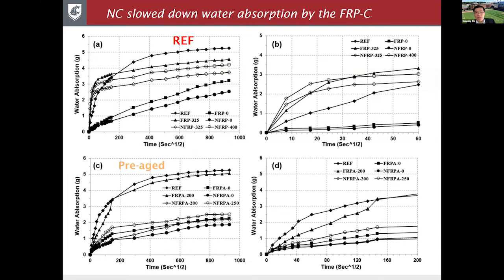Now, the nanoclay also slows down the water absorption. On the top is the reference group without any FRP; I should call it the new concrete group, and the bottom is the pre-aged group. On the right-hand side is just the first initial stage of the absorption. Basically, the surface area under each curve is the amount of water absorbed during that time. Of course, the reference one is the black one at the very top, so that absorbs the most water. In other words, for both the new and pre-aged group, once you have FRP or nanoclay, either way, they're reducing the amount of water incorporated, and also they're slowing down the water ingress. So you can see the difference.